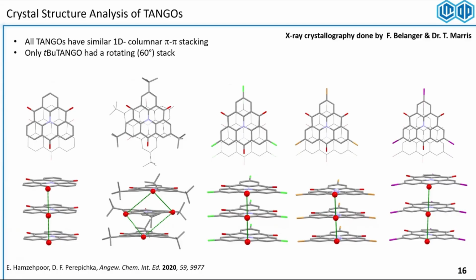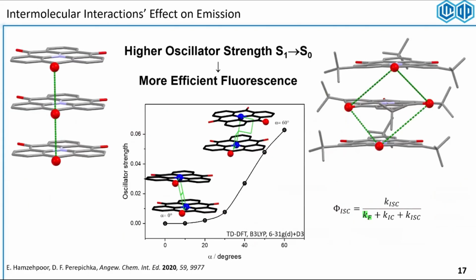We were delighted to see that they're actually all packing roughly the same in their solid state, having this nice columnar pi stacks sitting next to each other because of the flat nature of the molecules. And it was only in the case of the tertiary butyl Tango where the molecules were rotating 60 degrees on top of each other to accommodate for this steric hindrance of tertiary butyls, but still have these flat pi stacks dominant in their crystal structure. So this rotation, that change in the luminescence of the solid versus the rest that were face-to-face packing, we wanted to see why is that.